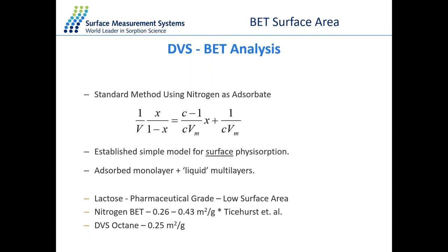So why linearity? Here you can see the BET, Brunauer-Emmett-Teller equation. The way this equation is presented is the equation of a line. It tells you that y equals mx plus q. So as long as the plot is linear, we can fit a line in the section of the monolayer between 5 and 30% partial pressure.